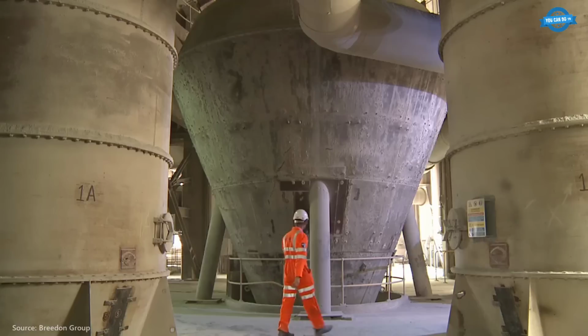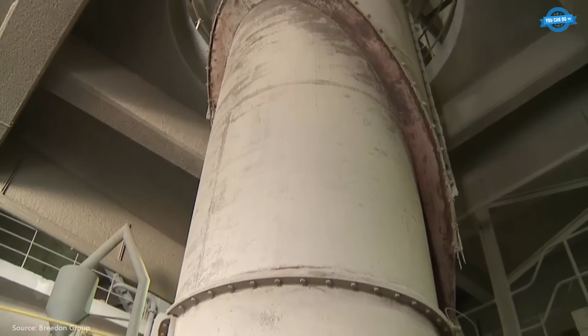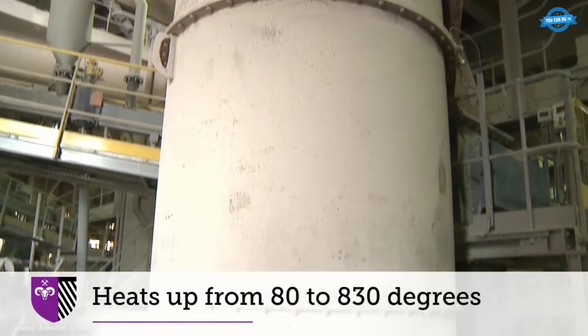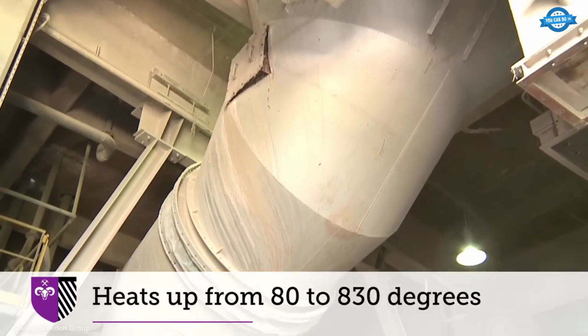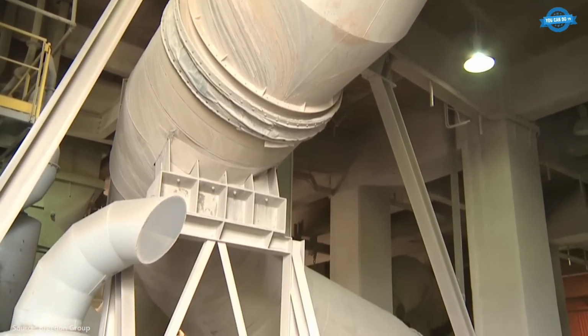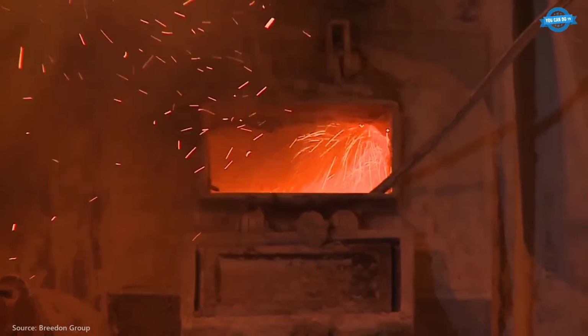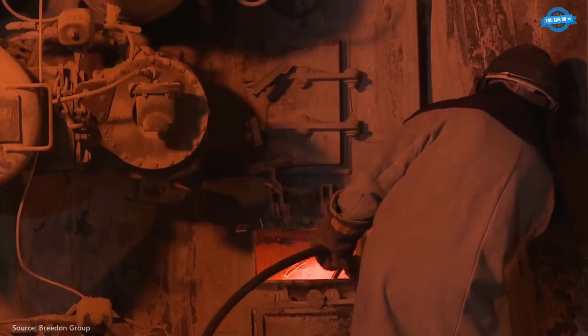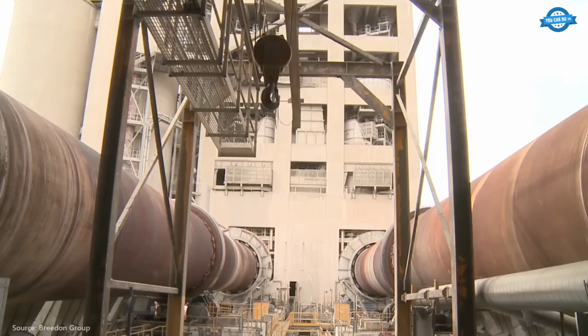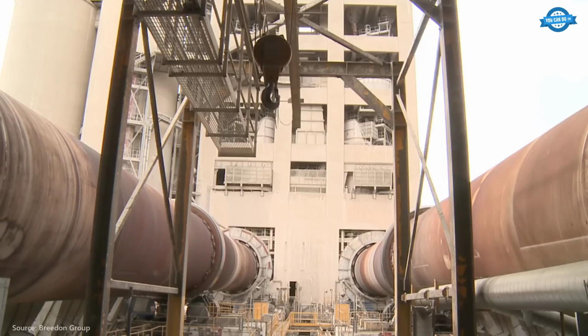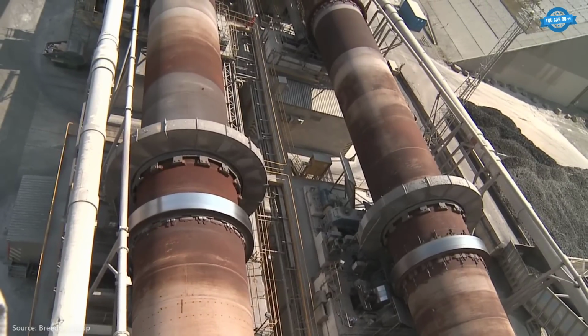The preheated material is fed into one of 2 massive kilns, each 70 meters long and 4.8 meters in diameter, lined with 70,000 heat-resistant bricks. The kilns operate at temperatures exceeding 1,500 degrees Celsius, enabling the chemical transformation of the raw material into cement clinker.